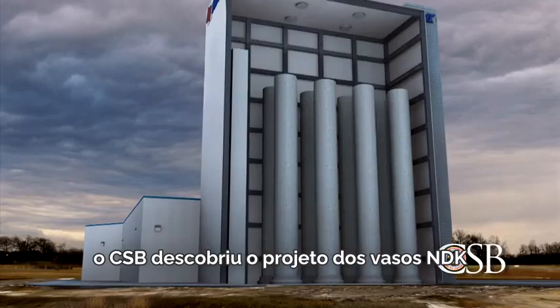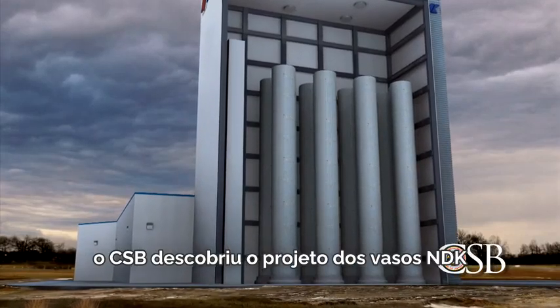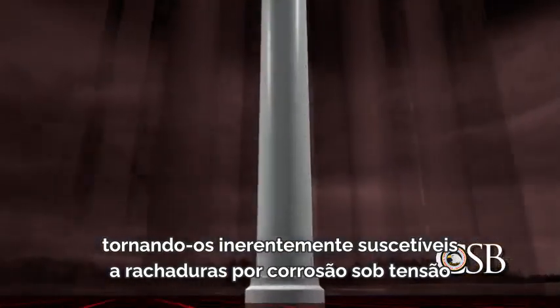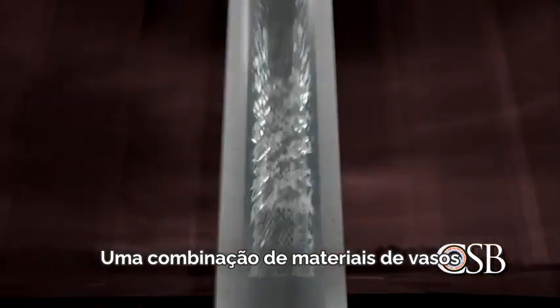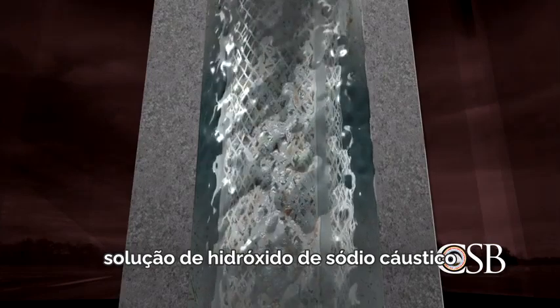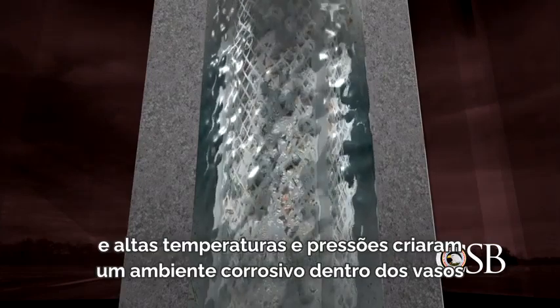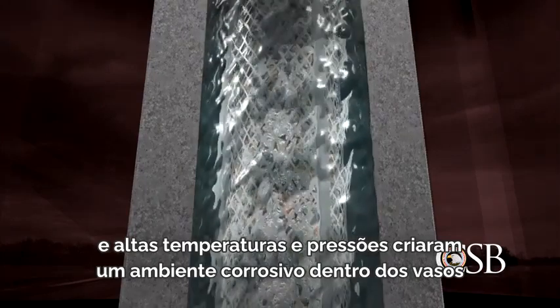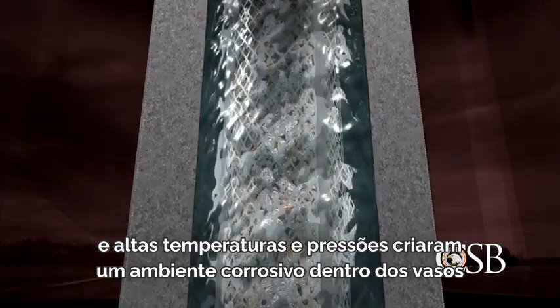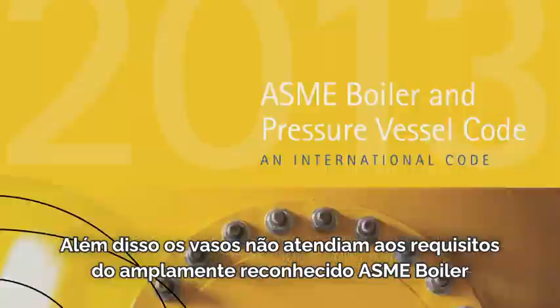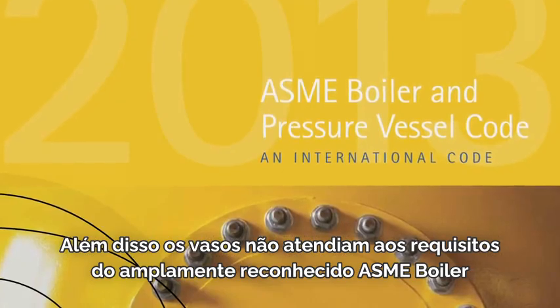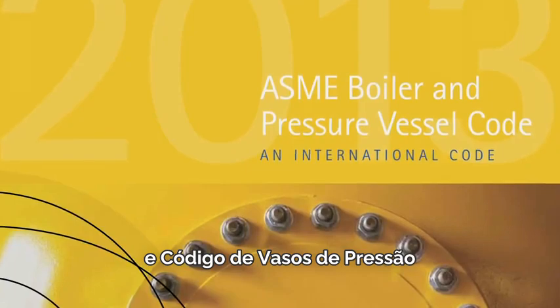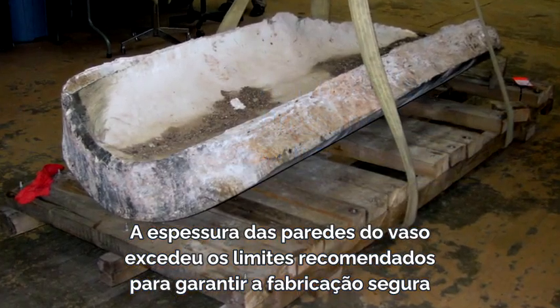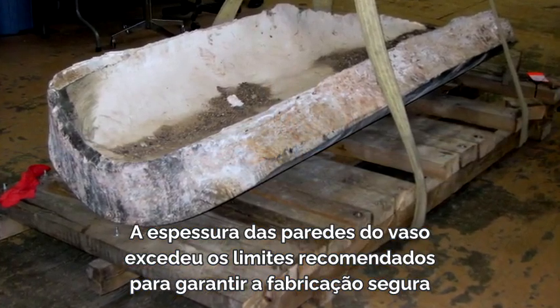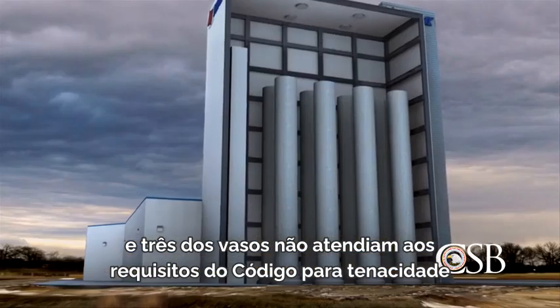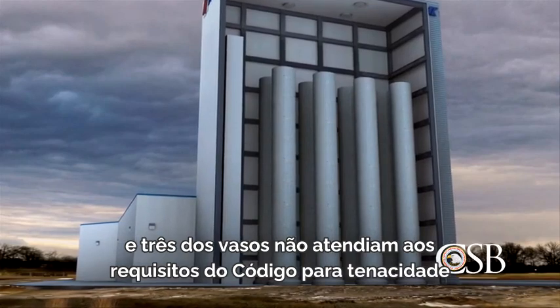In addition, the CSB found the design of the NDK vessels made them inherently susceptible to stress corrosion cracking. A combination of vessel materials, caustic sodium hydroxide solution, and high temperatures and pressures created a corrosive environment inside the vessels. Also, the vessels did not meet requirements of the widely recognized ASME boiler and pressure vessel code. The thickness of the vessel walls exceeded recommended limits to ensure safe manufacturing, and 3 of the vessels did not meet the code's requirements for toughness.